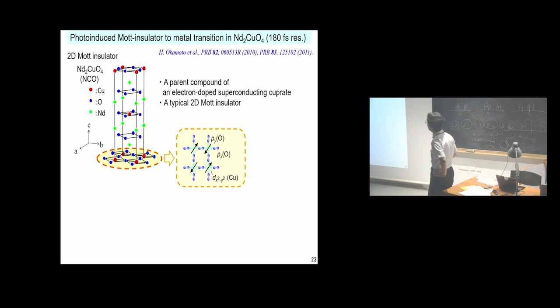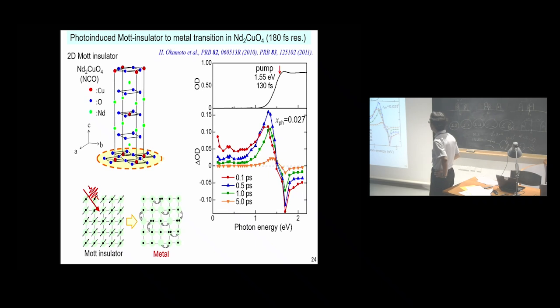Let's move on to the 2D Mott insulator. Here we focus on this compound, neodymium cuprate Nd2CuO4, which is a parent compound of an electron-doped superconducting cuprate and is a typical 2D Mott insulator. In this figure, this solid line shows the optical density spectrum, that is the absorption spectrum, and color marks show the photo-induced absorption changes, delta OD. The time resolution is about 200 femtoseconds. The spectra are complicated as compared to those observed in 1D Mott insulators.